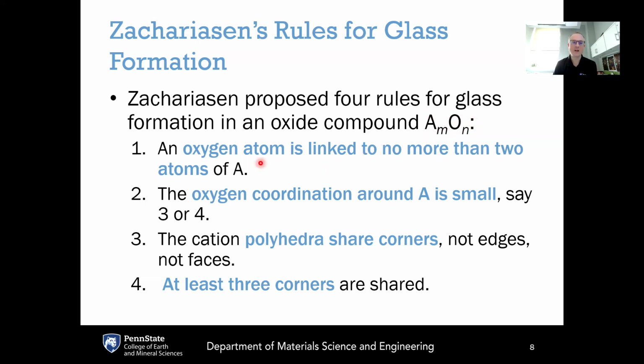The first rule is an oxygen atom is linked to no more than 2 atoms of A. In other words, the oxygen is the anion, it has a charge of -2, and it is linked to no more than 2 of the cations A in order to satisfy that charge balance. The second rule is that the oxygen coordination around the cation A is small, say 3 or 4. So combined, these first 2 rules are defining the short-range order, which is found in glasses.